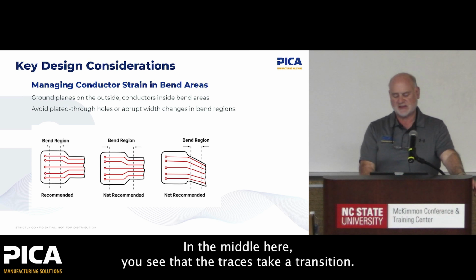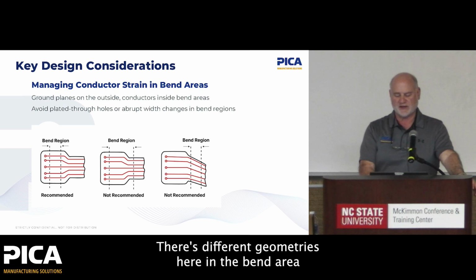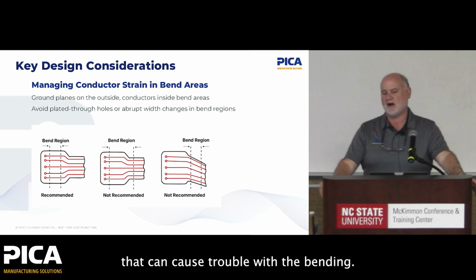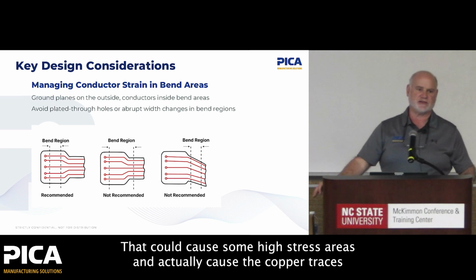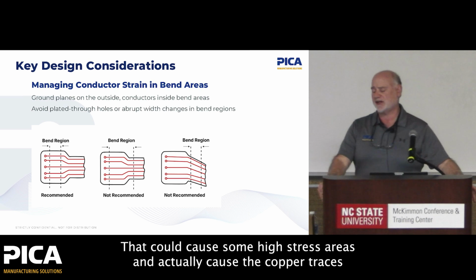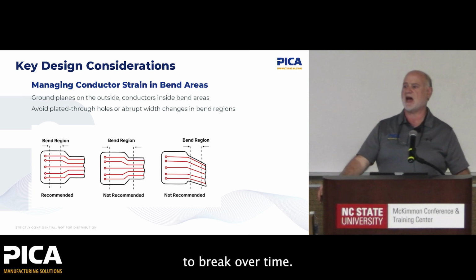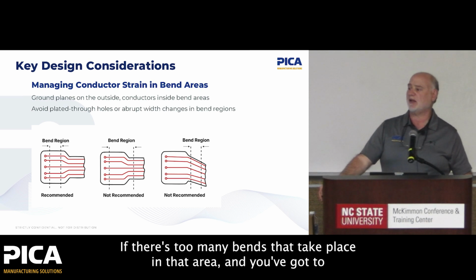In the middle here, you see that the traces take a transition. There's different geometries here in the bend area. That can cause trouble with the bending. That could cause some high stress areas and actually cause the copper traces to break over time if there's too many bends that take place in that area.